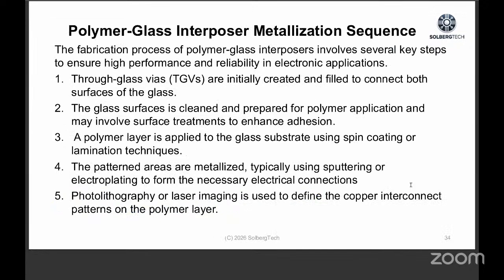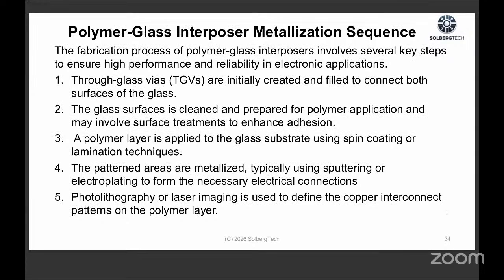Next slide. So the interposer metallization sequence, we begin with the through glass via, initially created and filled to connect both surfaces of the glass. The glass surface is cleaned and prepared for polymer application, and that may involve surface treatments to enhance adhesion. The polymer layers are applied to the glass substrate using spin coating or lamination techniques. Patterned areas are metallized, typically using sputtering or electroplating to form necessary electrical connections.